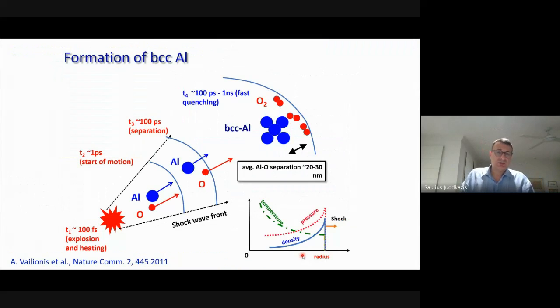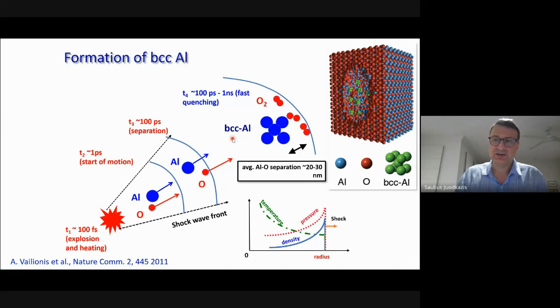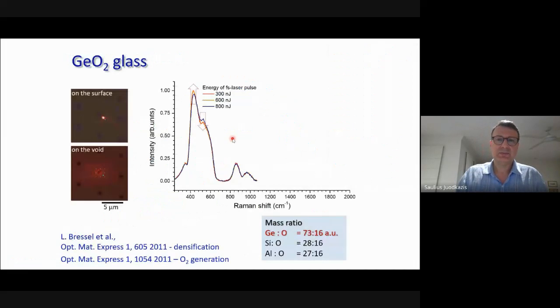This is a cartoon picture of what is happening once we ionize material. Triply or even 4 times ionized aluminum and oxygen are flying from the explosion, the central energy deposition site, and then it's thermally quenched. It's experimentally obvious that there will be some conditions in which we capture this BCC phase. And it is around the ablation site.